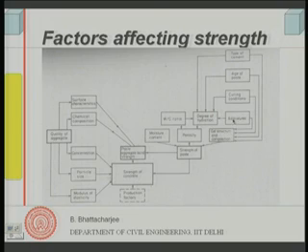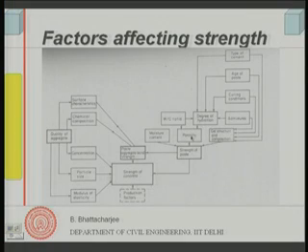Now, admixtures can also control the degree of hydration, because you can have something like accelerators or retarders. So, this can govern the degree of hydration, which together with water cement ratio controls the porosity, and degree of hydration is also governed by curing condition, age and type of cement. So, finally, you can see strength of concrete is governed by all these factors,